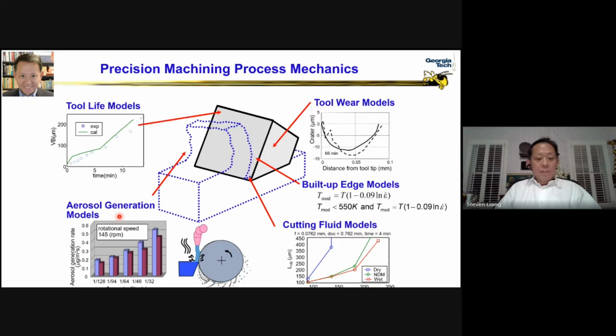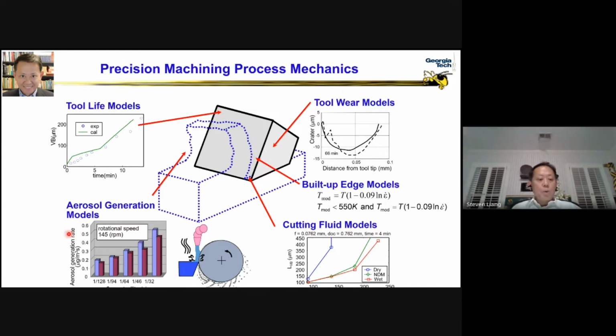So we have worked with a lot of industry companies to look at the control of process parameters in order to curb the generation of cutting fluid aerosol from several mechanisms: cutting fluid splash, spin-off, evaporation, perturbation in the air, as well as consolidation. And this turned out to be quite effective already without using the wet mechanism. What we have developed here is near dry machining, NDM, just spraying a very small amount of cutting fluid in the cutting zone. The effect of protecting the cutting tool would be just as good. And so this is the use of minimum quantity lubrication to maximize the performance of machining.